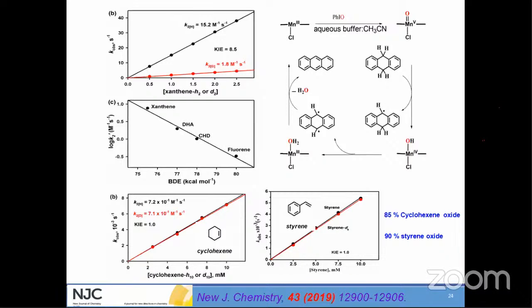Then, to support this mechanism, we took different substrates, found out their k2 values, that is the second order rate constants, and then compared those values with their bond dissociation energies, that is the C-H bond dissociation energies. Those BDE values are already reported and known. They are taken directly from the literature.